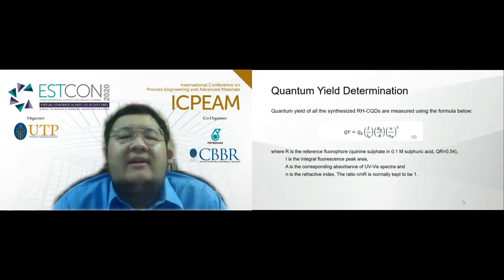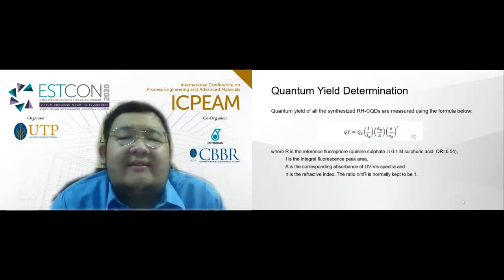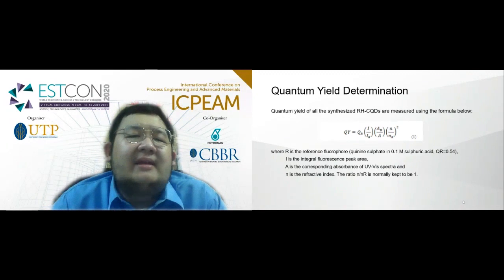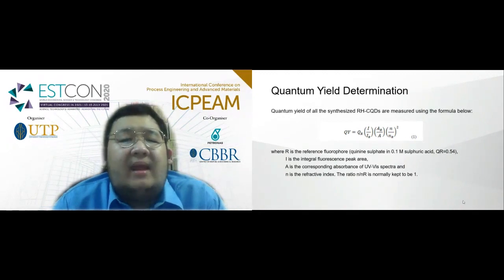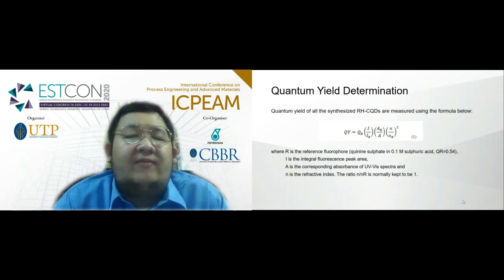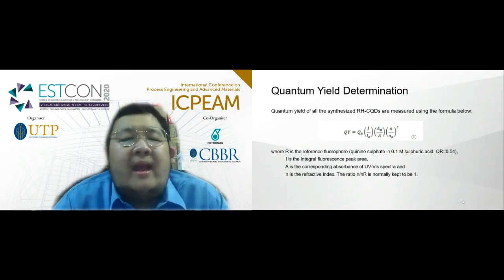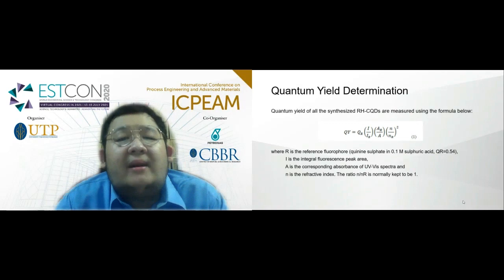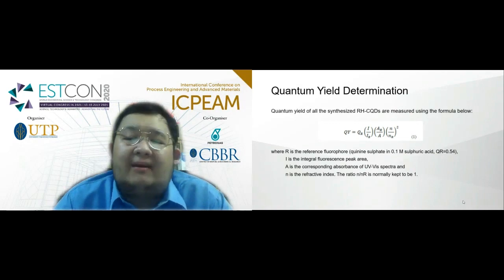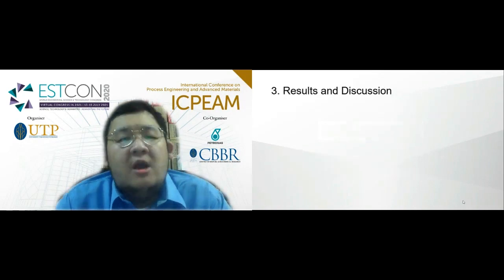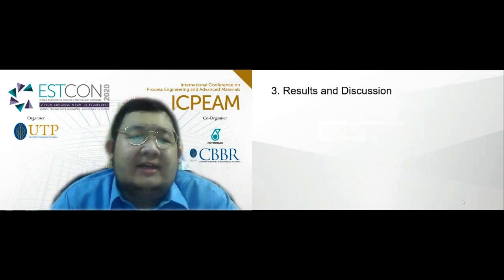It is calculated using the formula below, whereby R is the reference fluorophore, in this case quinine sulfate, in which QR is normally 0.54. I is the integral fluorescence peak area. A is the corresponding absorbance of the UV-vis spectra of the respective CQD sample. N is the refractive index, whereby the ratio of N over NR is normally kept to be 1. Moving on to the results and discussion.